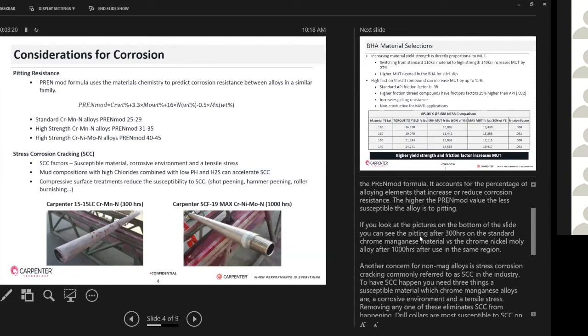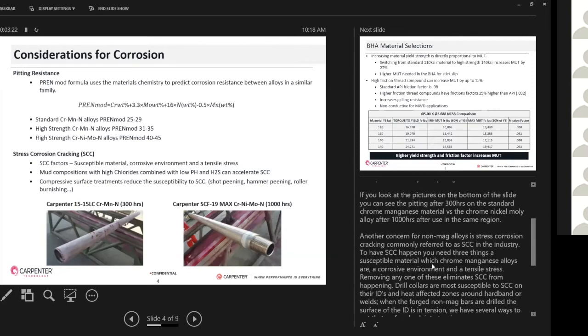So if you look at the two pictures on the bottom of the slide there, you can see the pitting after 300 hours on the standard chrome manganese alloy versus the chrome nickel alloy after 1,000 hours. Both of them were used in the same region, in the same types of environments.